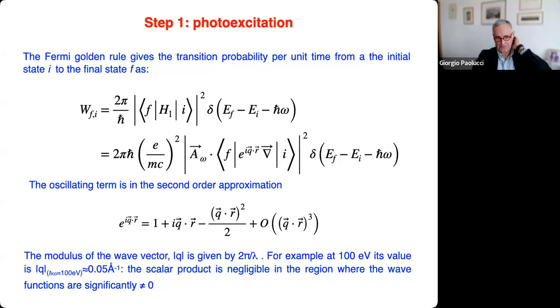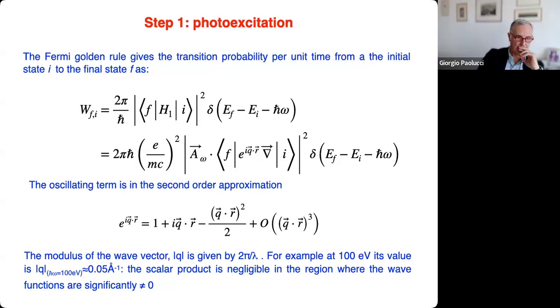And because the modulus of the wave vector of the incoming photons is 2 pi over lambda, which means that at 100 eV it is of the order of 0.05 angstrom to the -1. And because we are talking about distances of the order of angstrom, now 1 times 0.05 is, of course, a very small number. So we simply forget anything which is after 1 in this expansion.